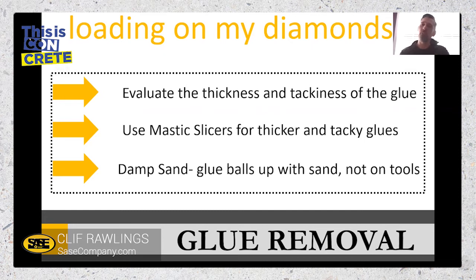Now we say put it into a 5-gallon bucket, mix a little bit of water into it so it makes it damp sand, not wet but damp. And now it keeps it from being airborne. It still balls up and sticks to the glue and doesn't stick to your tooling, and you don't have the airborne issue as well. So it works really well using damp sand, whether it be just a metal bond, PCDs, or these new Mastic Slicers we're going to cover. The damp sand helps a ton when you're dealing with really sticky glues.